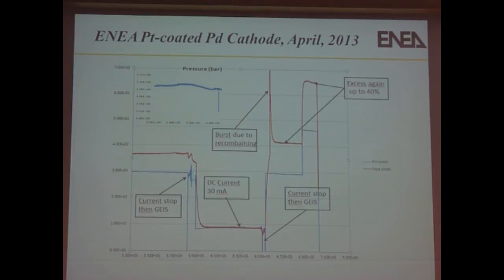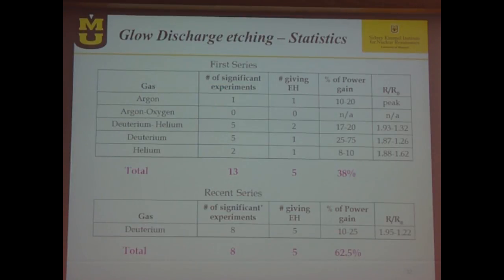And the more we went in this direction, the better we saw that this parameter actually helps us to screen the cathodes and to know which cathodes are more likely to produce excess heat. And again, this is another one, from an experiment in 2013 made at ENEA, and you can see again 40% and 30% and so on. And that direction is very promising.